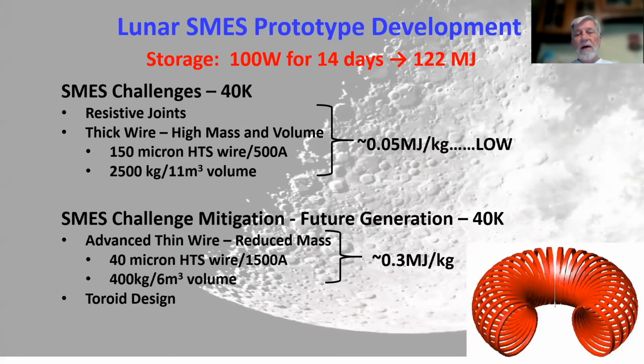So let's look at what the challenges are. At 40 degrees Kelvin, we have the resistive joints. We have thick wire currently, high mass and high volume. It turns out that if we want to do storage of 100 watts for 14 days, that's 122 megajoules. We need a coil that has about 2,500 kilograms of mass and a volume of about 11 cubic meters. That means the energy density, about 0.05 megajoules per kilogram, is really quite low.